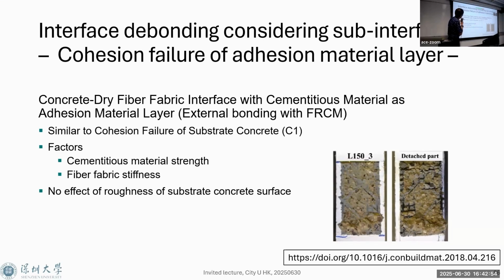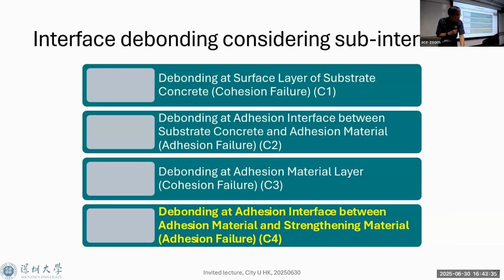Then this is a debonding case in terms of a concrete dry fiber fabric sheet with cementitious material. In this case, debonding takes place within the adhesion material. In this case, the adhesion material is a cementitious material, same as the substrate concrete. So if debonding happens within cementitious material, like concrete, then the bonding nature is similar to the first case. So you have to be very careful where your debonding takes place.